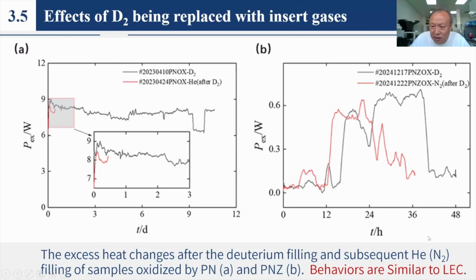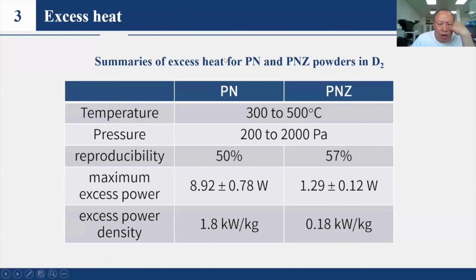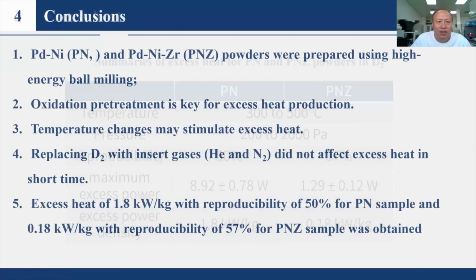This result is similar to the LEC behavior. This is a summary of our samples for PN and PNZ. They also worked in temperatures of 300 to 500 degrees. Pressure is 200 to 2000 pascals. Reproducibility is 50% to 57%. The maximum excess power is about 9 watts and 1.3 watts, and excess power density is 1.8 kilowatts per kilogram or 0.18 kilowatts per kilogram.